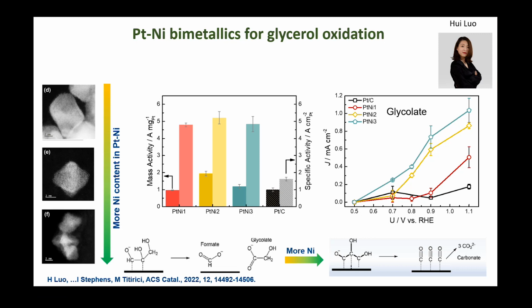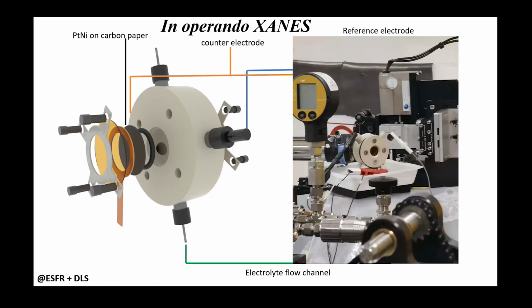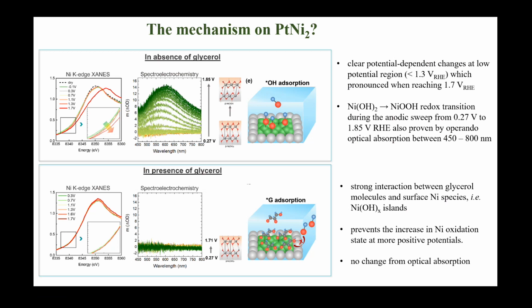So this material, platinum nickel 2, where I said there is one platinum near one nickel atom, you would see that it has the highest mass activity and also the highest specific activity. So we selected this material to look in operando with XAS at ESRF and Diamond Light Source to really understand better the mechanism through which this catalyzes the glycerol oxidation. Very interestingly, first we thought, if we would have a platinum atom and a nickel atom, that we would have independent OH and carbon intermediates adsorbed on these different sites. And so we wanted to see if that would be the case. But in fact, we've seen that that's not the case.